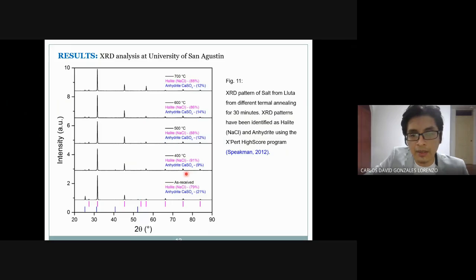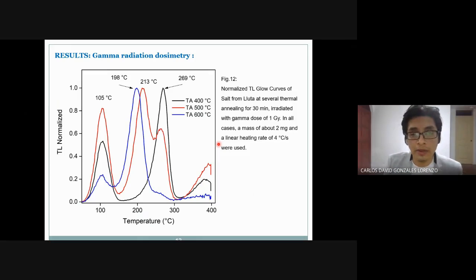Okay, and so on with the other samples. One important result here is for the sample with a previous thermal treatment of 400 degrees Celsius. This sample shows the greatest quantity of halite, about 91%, and anhydrite about 9%. For the other samples, the quantity of halite and anhydrite is almost maintained at about 88% and 12%. Okay, in this figure I show you the glow curves of salt from Lluta at several thermal treatments for 30 minutes, irradiated with a gamma dose of 1 gray. In all cases, about 2 milligrams and a linear heating rate of 4 degrees Celsius per second were used. For each previous thermal treatment, we can see different glow curves.